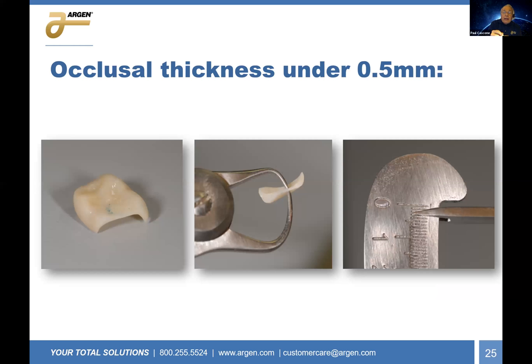Okay. Now, zirconia is not indestructible, regardless of what people may have said before. If you get below those minimum values with the strength of zirconia you're using, as we have here, an occlusal thickness of under 0.5 millimeter, and this material has a strength of 1,100 megapascals, it fractured, and it fractured very early in its life. And again, it's strictly because the material just can't tolerate that amount of stress.